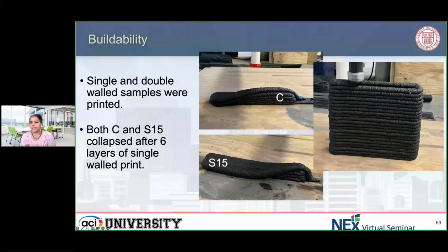layers. So again, buildability depends on what you are trying to achieve, because there are no standards for buildability, extrudability, green strength right now. You'll have to decide what's a good test for you, and it all depends on, at the end of the day, what do you want to do with these material systems. In our case, what we were doing is we were taking these samples and then we were cutting them, and then we were doing flexural strength to measure the bond strength between, which I'll show you in the next slide. So this is a sufficient print to be able to do.